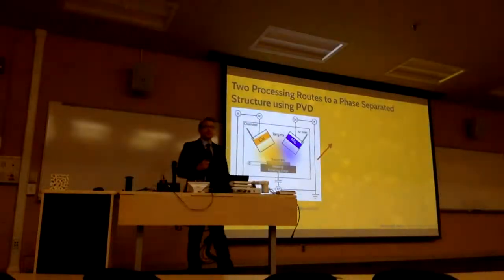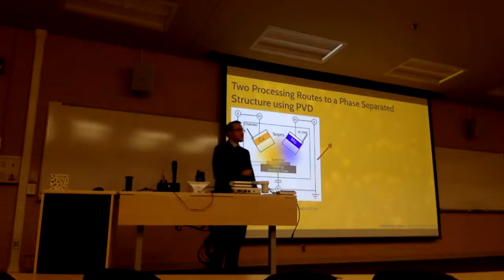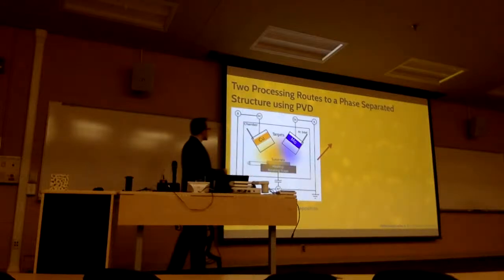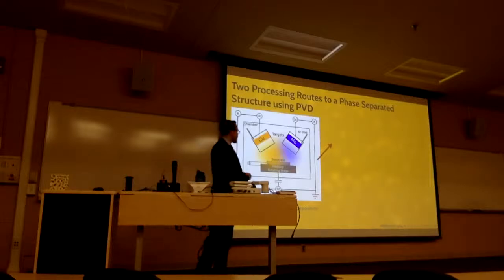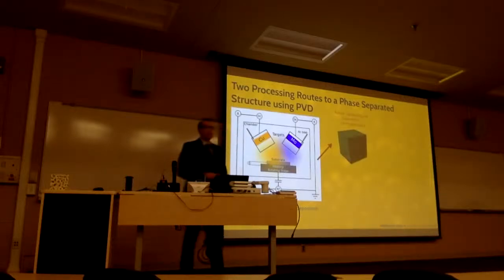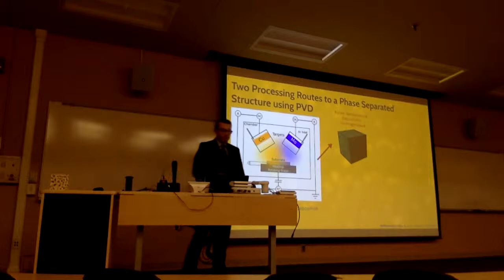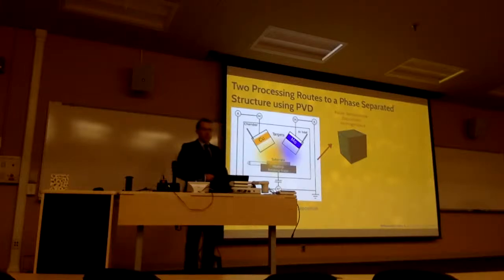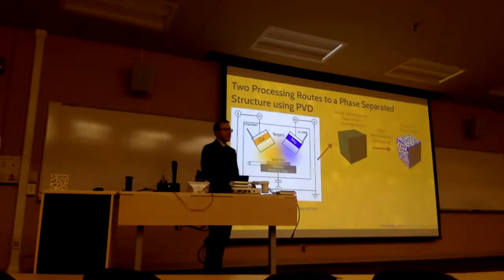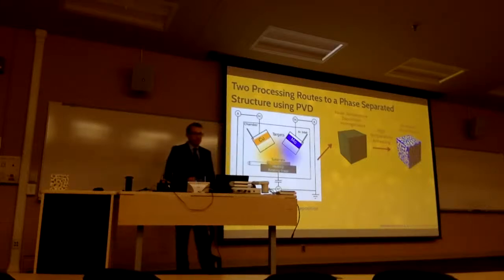So you can imagine doing this a few different ways using physical vapor deposition. Take, for example, we have a copper target and a moly target. We condense that onto a substrate. We might form a homogeneous alloy like I described before. We deposit an equal amount of those two materials. We could heat it up, and we could form this 3D bicontinuous-like structure that I described before.